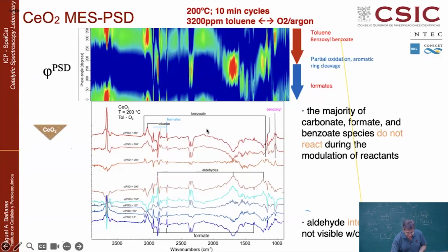So you see that sometimes some bands are like this benzyloxy, which is being formed, decreases, and is being consumed here. So benzyloxy forms when you are feeding the toluene, goes through a maximum, starts to decrease, and then when you cut the toluene off, it decreases, and then when you start to feed the toluene, it starts to grow. And the same thing is happening with this species. It's being consumed, and then it's being developed, and it's being consumed.